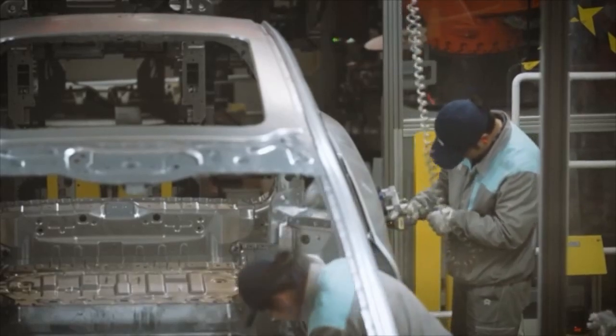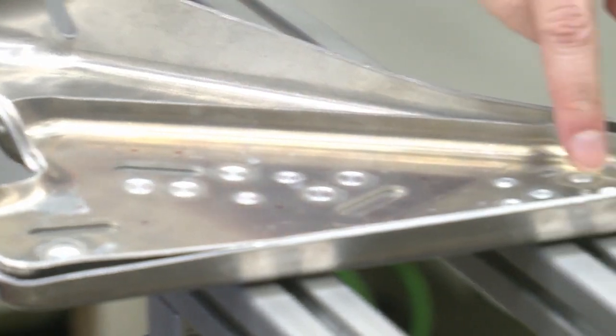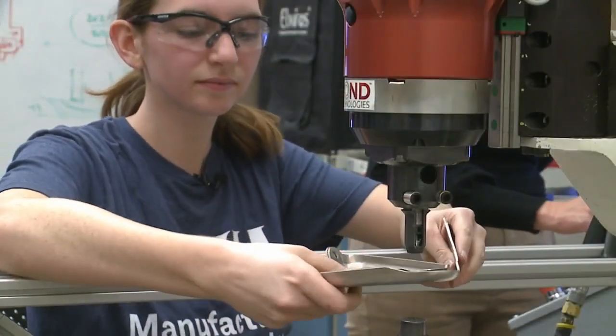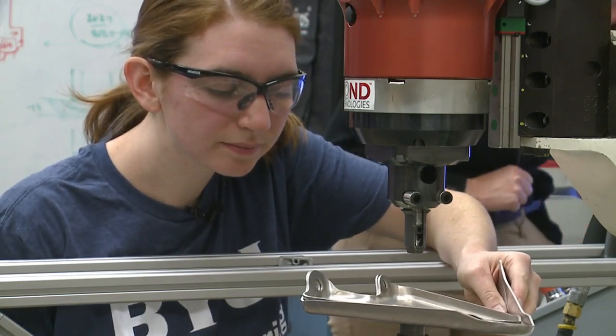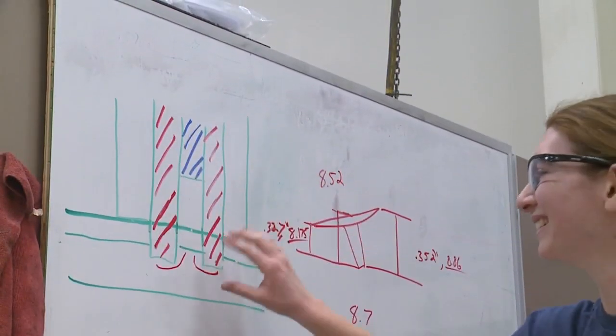We dropped it for Toyota down to 250 milliseconds. This type of spot welding that students are developing and researching uses 40 times less energy, emits fewer emissions, and creates welds that are 10 times stronger.